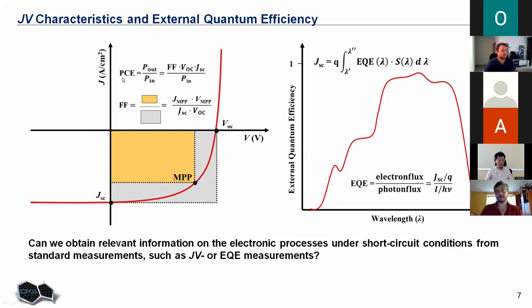And we see that the most important parameter of solar cells, which is PCE, stands for power conversion efficiency, is the ratio of the product of fill factor, VOC and short circuit current divided by the input power, which is incident on the surface of this solar cell from the sunlight. So we see that all of these three main photoelectric parameters should be maximum, and they should all contribute to higher PCE.